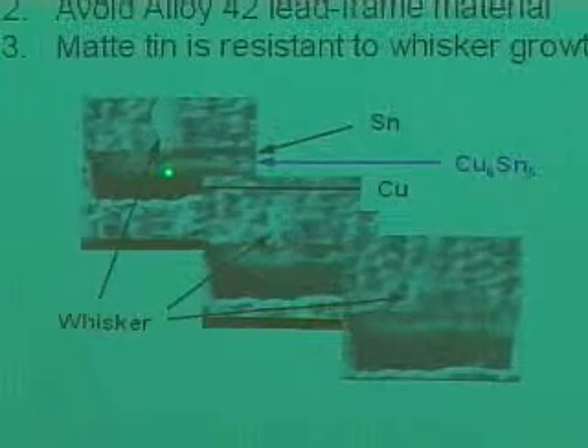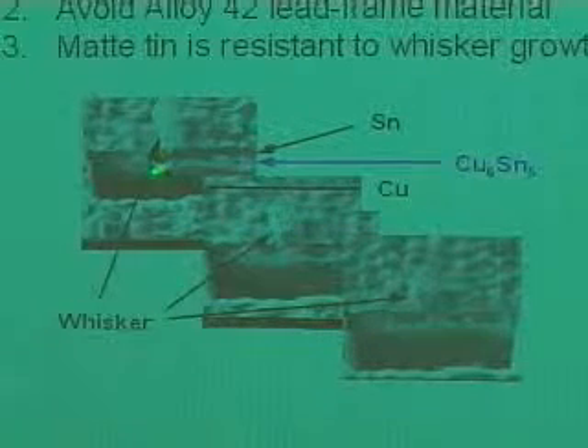In other words, how do you test for that? That's difficult. So here's some work that was published where they took cross sections. This is actually a whisker. They took cross sections just adjacent to it, and you can actually see where they've identified the intermetallic that's growing, in this case the copper 6 tin 5, and you can see the sequence in the growth here. And as the intermetallic's getting a little thicker, you can see the tin whiskers growing longer. And that's one of the experiments that's been cited for this particular model.